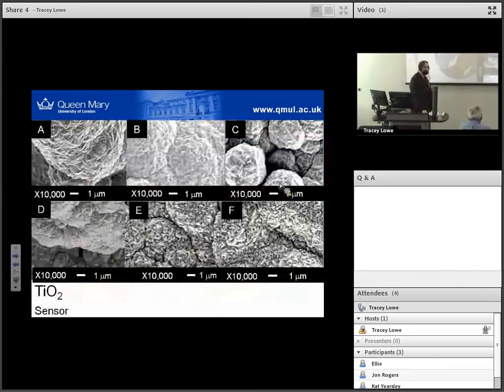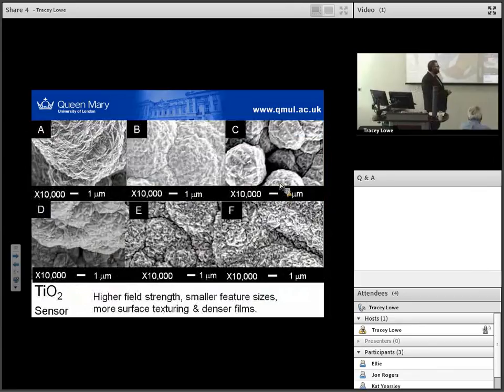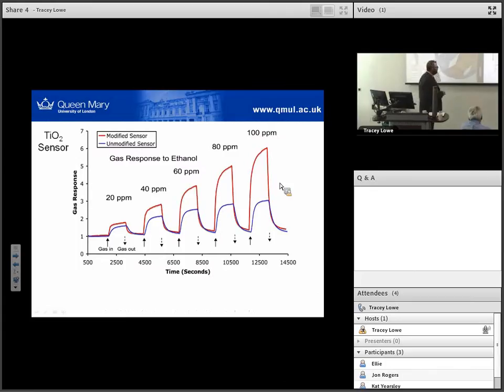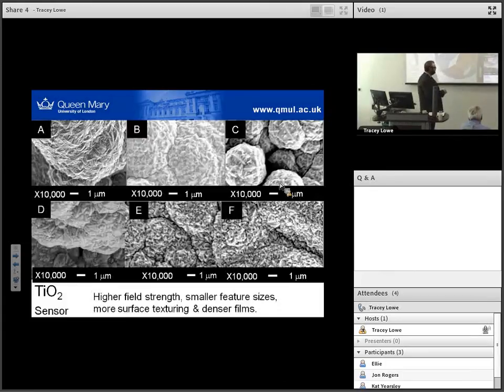So what about functional properties? These are the surfaces of our titania. As we increase our field strength from A up to F - I've not got all the details because this has been IP protected - we see some strange changes in the surface, more surface texturing and a higher density in our films. For the majority of the films, that's actually a highly desirable thing; we get very nice sensor results.